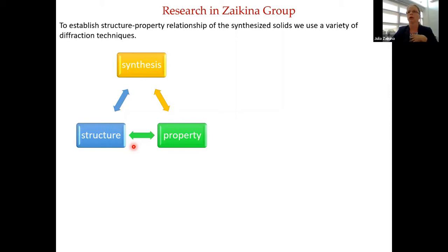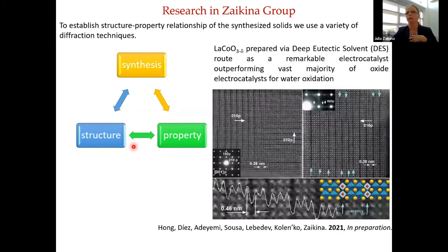And I want to show you the most recent example from our group, even though I promised not to talk about the deep eutectic solvent project at all, but this is a very recent result we obtained. So, lanthanum cobalt oxide is a known oxide, but when we prepare it via the deep eutectic solvent route, this material now features a lot of oxygen vacancies, which manifest themselves as those dark stripes in the scanning transmission electron microscopy image. And thanks to those vacancies, this material behaves as a really remarkable electrocatalyst for water oxidation.